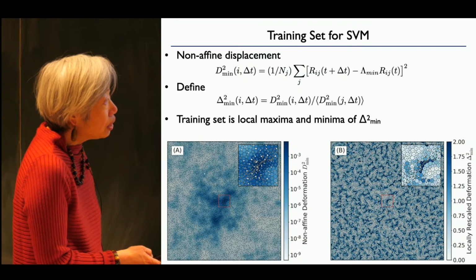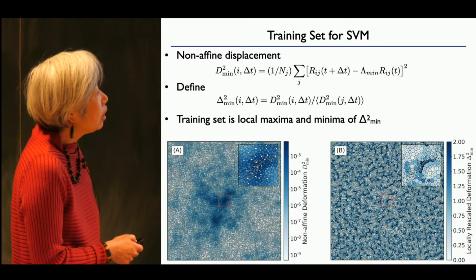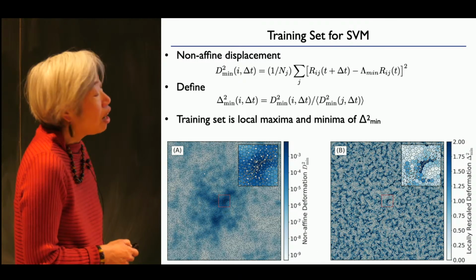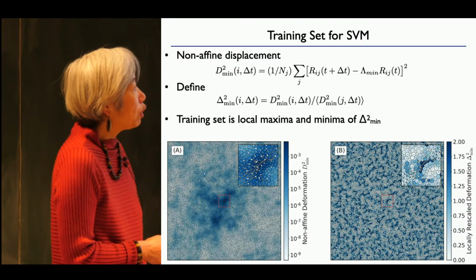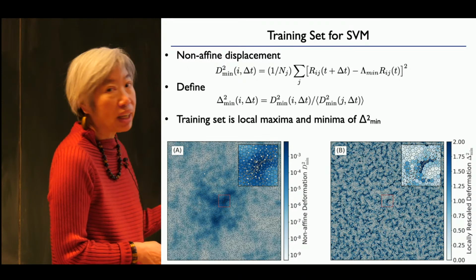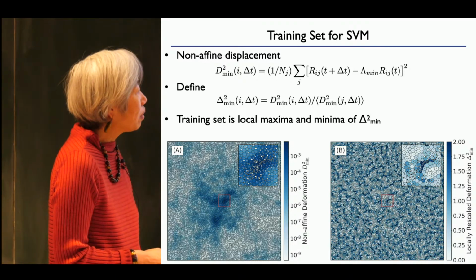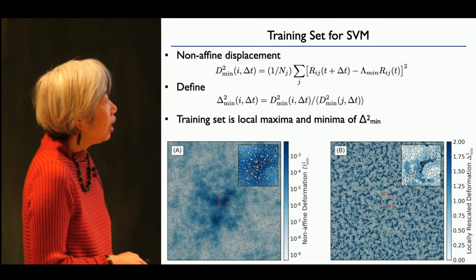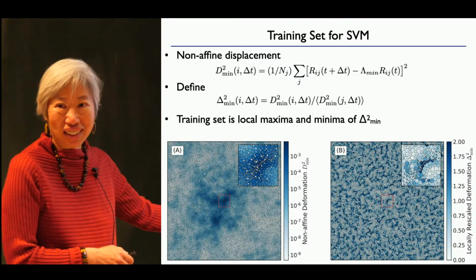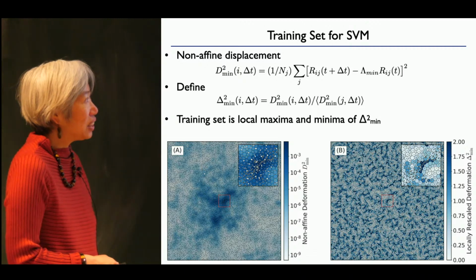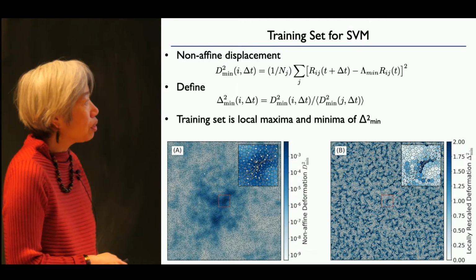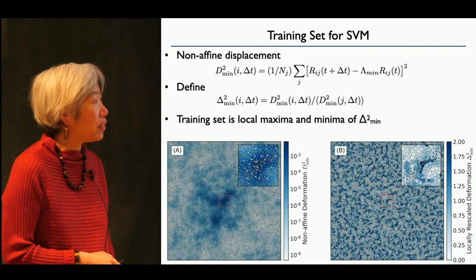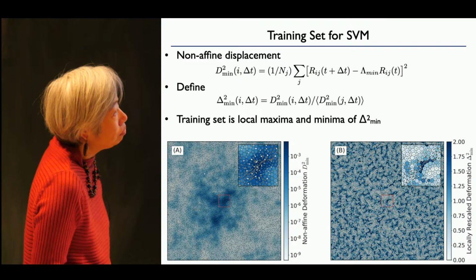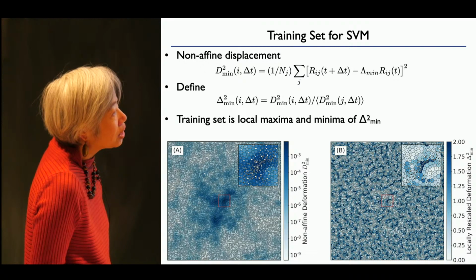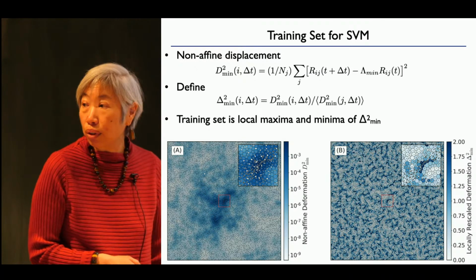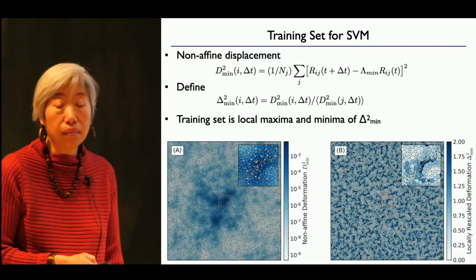And so the nice thing about this is that if we were to just use d squared min, our training set would just be the rearranging particle here and maybe some particle way out here, with a very small non-affine displacement. And that would be very wasteful of data. We don't have that many configurations from Misaki and Ludovic to be able to just use 2 particles for every configuration. So we train instead on local minima and maxima of delta squared min. So there you can see there are many of them.